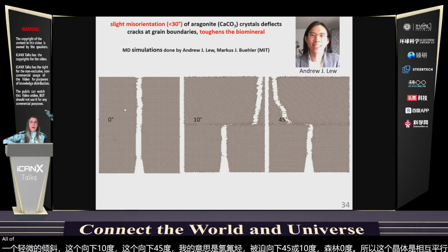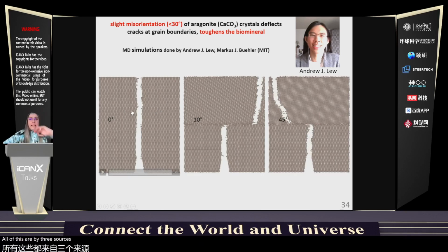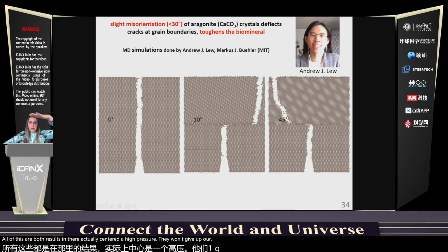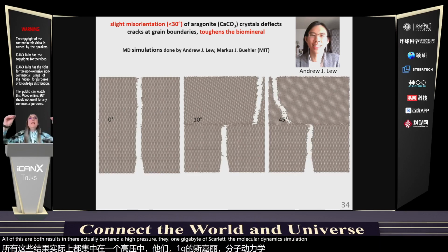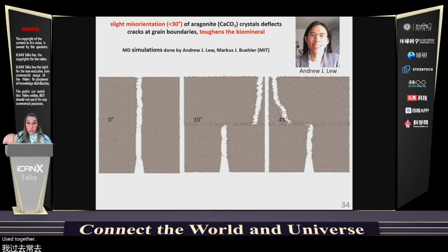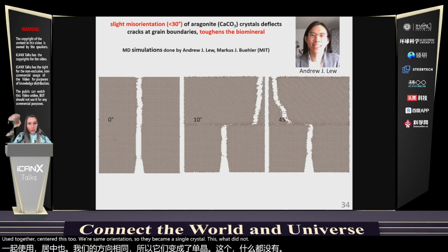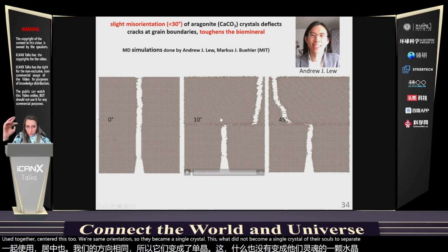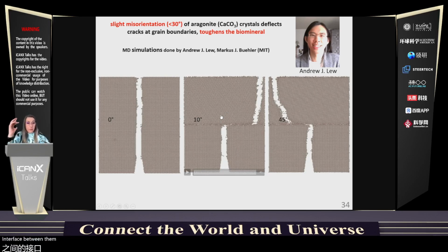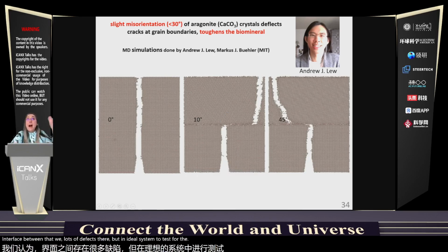All of these are bicrystals, and they're actually sintered at high pressure, at 1 gigapascal, in the molecular dynamic simulation. So they become fused together. These two were the same orientation, so they became a single crystal. These ones did not become a single crystal. They're still two separate crystals with a well-defined interface between them with lots of defects there, but an ideal system to test what a crack does at crystal orientation interfaces.